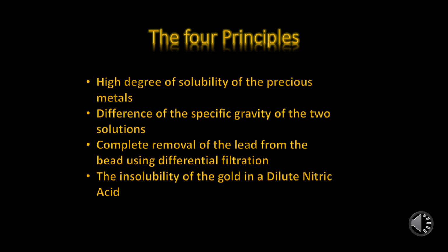The third is that the lead can be completely removed from the lead bead by way of the oxidation fusion, referred to as cupellation. It uses the methodology of differential filtration. The lead bead is oxidized to lead oxide, which is absorbed by the cupel, leaving the precious metal bead intact.